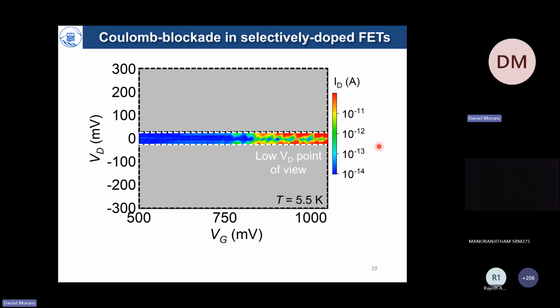Stability diagrams means measuring the actual absolute value of current in the space defined by gate voltage and drain bias. In that case, typically we measure by applying a few tens of millivolts to the source drain bias, and we can observe noise level current up to some point, and then so-called Coulomb diamonds successively arranged at higher voltages. These are signatures of single electron tunneling being observed in our devices.